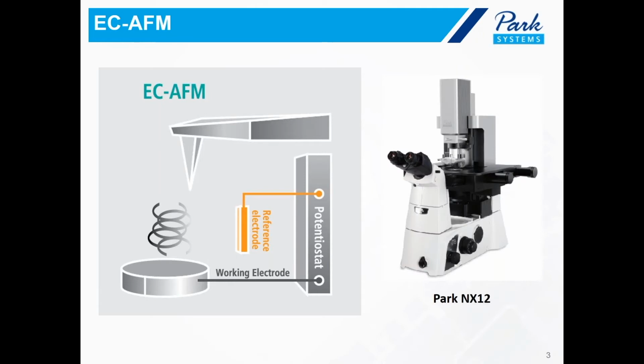In our experiment, the deposition and the dissolution of copper particles on the gold surface was successfully demonstrated. The morphological changes of the copper particles were clearly observed in situ using our new Park NX12 AFM. And a current-voltage, or CV, curve was simultaneously acquired using the potentiostat, which we combined with the system during the experiment.